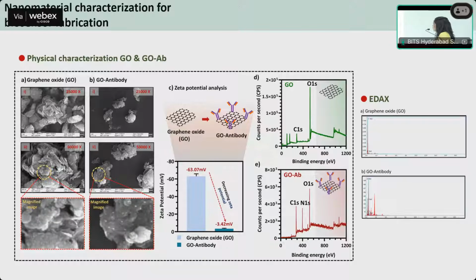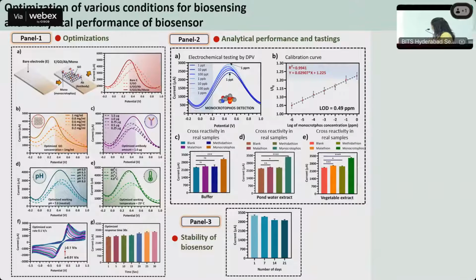So we have done the fabrication using GO in this case and immobilized the antibodies. These are the SEM images of the same, and zeta potential gave us a tremendous decrease in the charge, from -63 to -3, and that's the XPS and EDX analysis, which again confirmed the binding of the antibody. And the electrodes were again optimized for efficient performance.